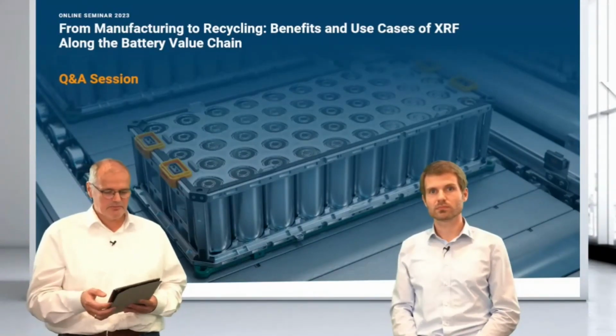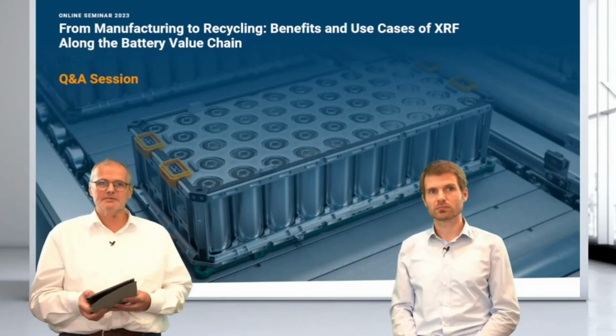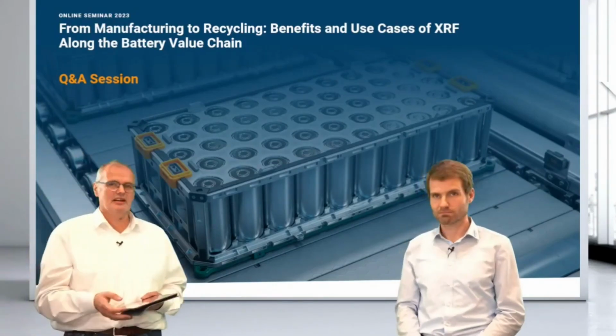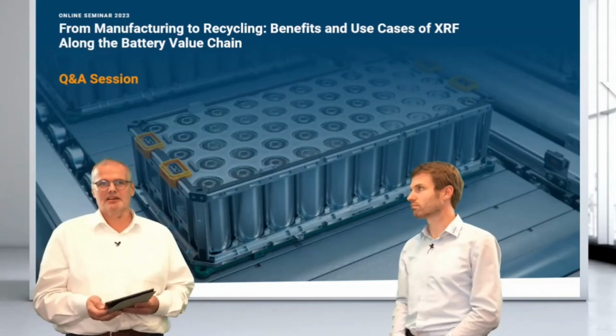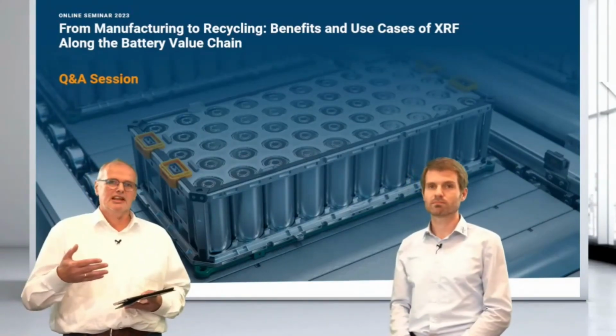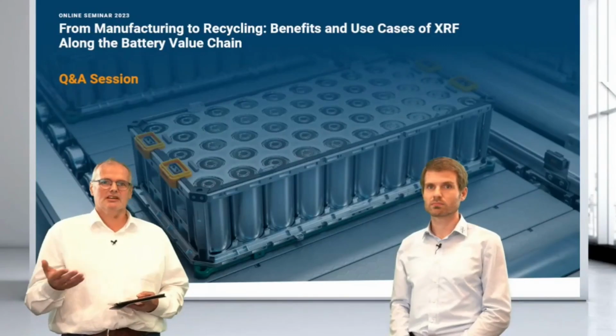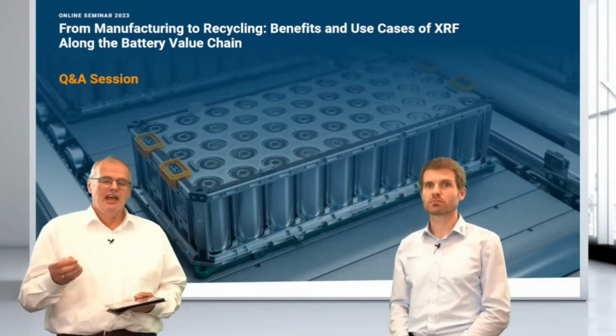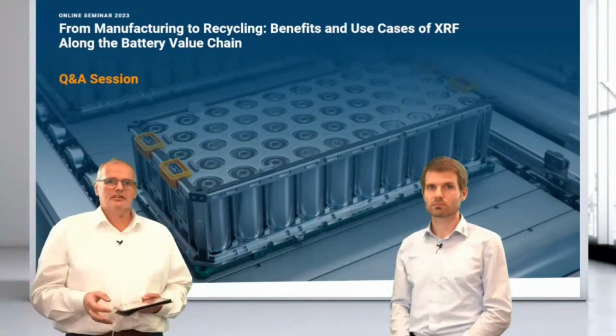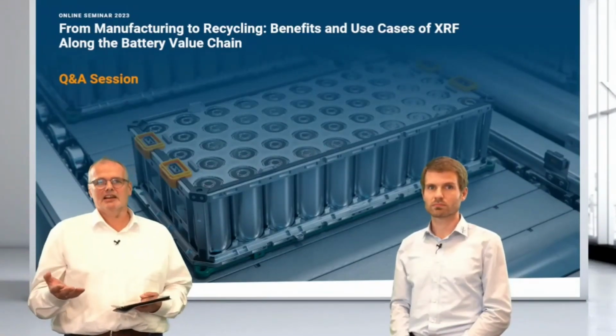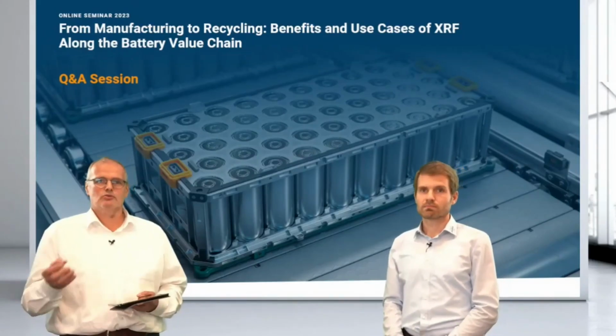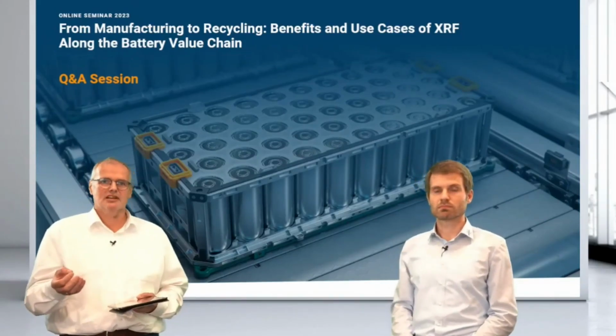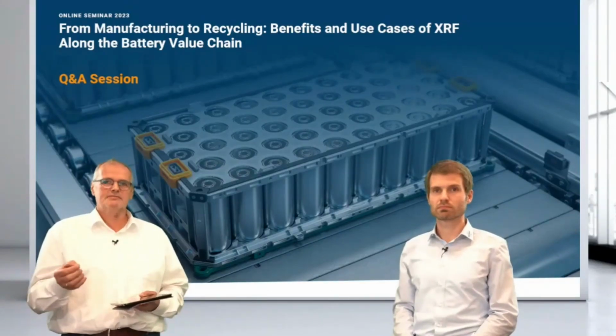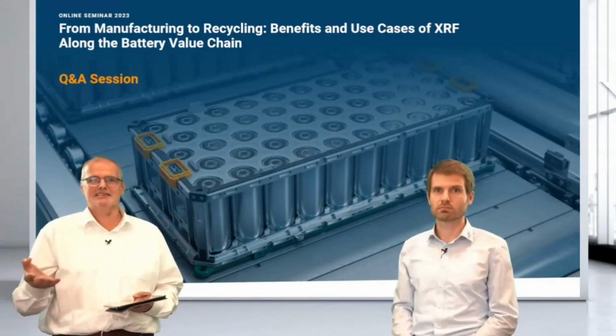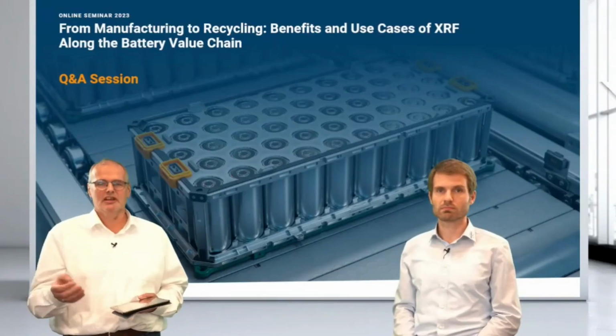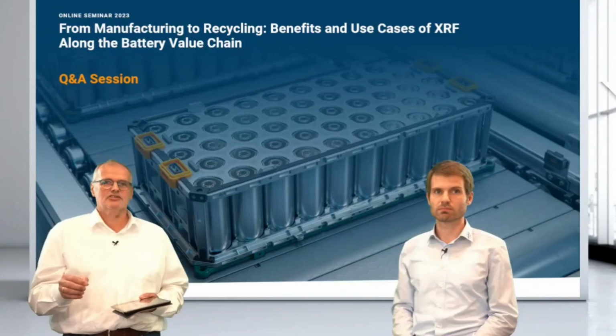There is another question. Please explain the benefits of XRF over LIBS. When we look at recycling, often LIBS comes into discussion. And of course, laser-induced breakdown spectroscopy is looking at surfaces. The major difference between those two methods is that XRF is a bulk analysis method, so we are looking at larger material amounts, a larger material volume. LIBS actually looks at a small spot where the laser hits the surface and creates the plasma. And this is the major drawback.